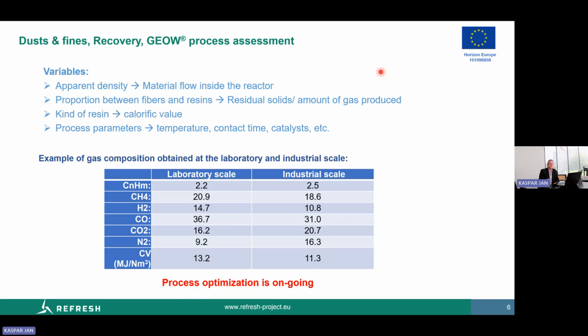And at first we have to resolve many problems which are due, for example, to transport of the materials, because the apparent density is sometimes very low, which means that you need an effective transport within the continuous reactor. We must find the appropriate conditions, because the proportion of fibers and resins is quite variable. As I showed before, it may be between 30 to 70%, so very wide conditions. And of course, the amount of gas produced is strongly dependent on this proportion. Clearly, the kind of resin also impacts the calorific value.